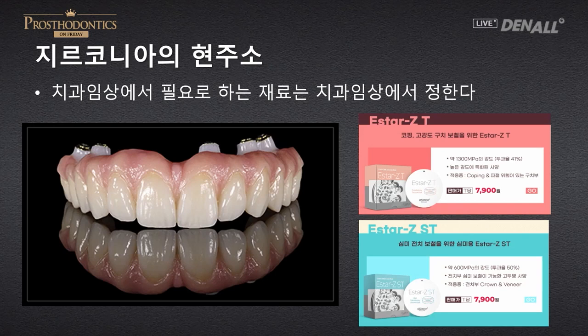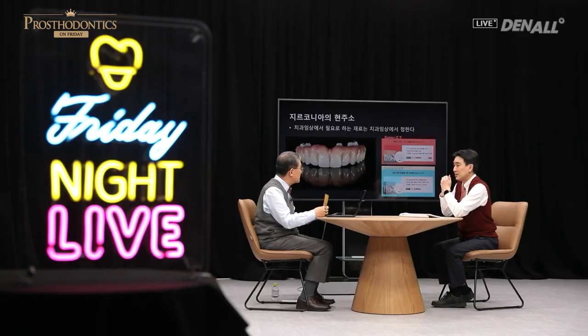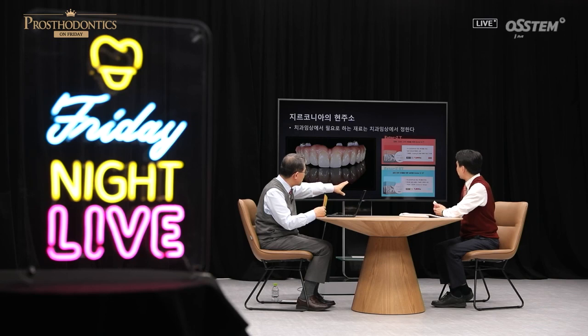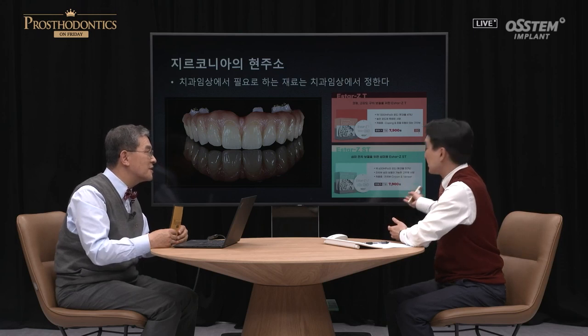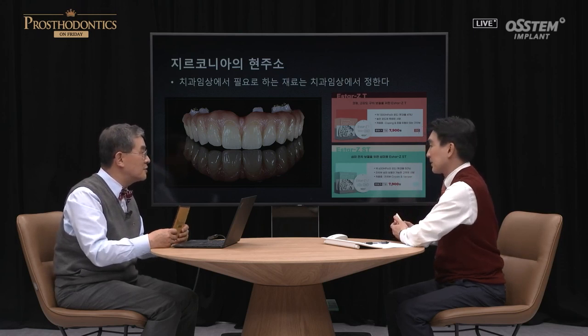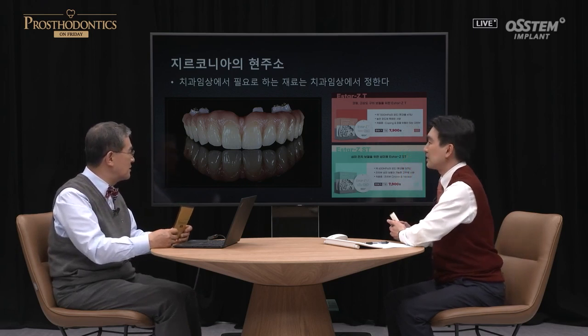Over here, it is 1300 megapascal. The high transparency block is 600 megapascal. It's less than half. Some may think, how can you sell this? But aesthetics is important, and strong force is not applied in the anterior area, and therefore you may use these blocks. Estar-Z is an Osstem product. In the case of Estar-Z ST, it is 600 megapascal. Is that hybrid? This is zirconia. It depends on how much yttria content it has. Yes, that's why the hardness has dropped.